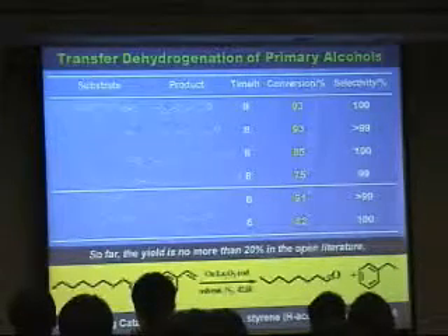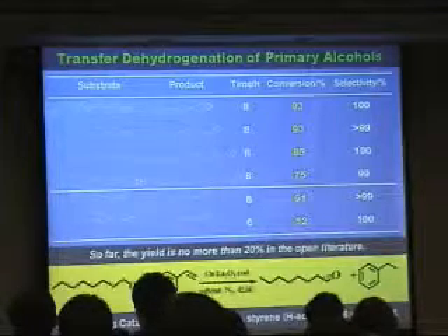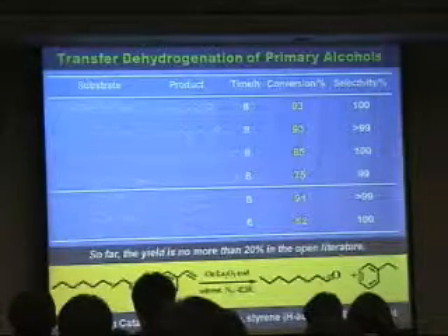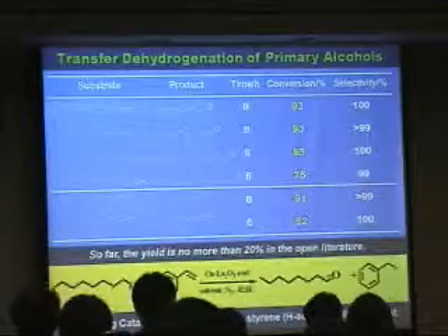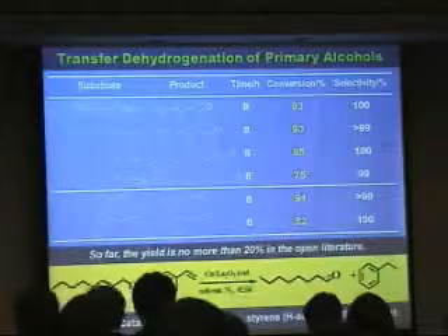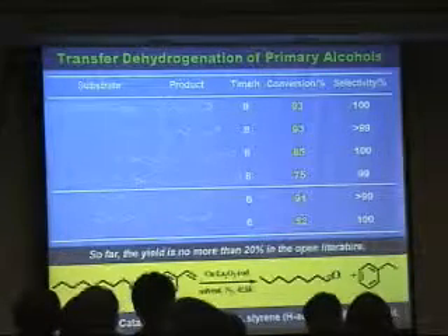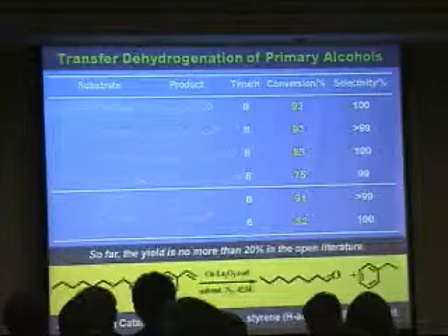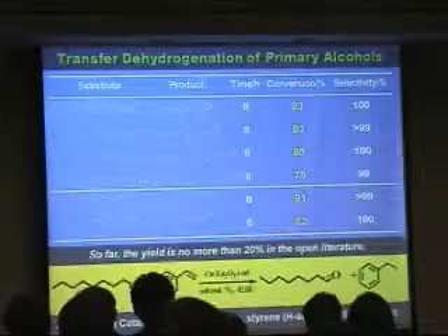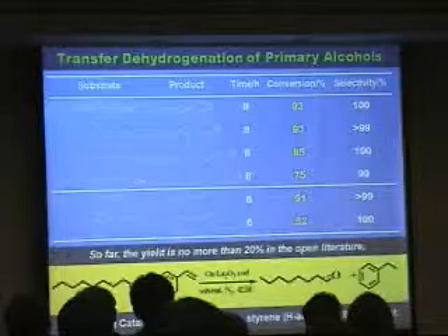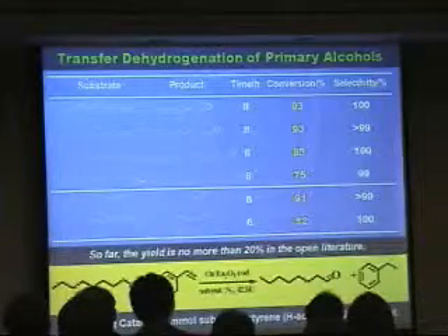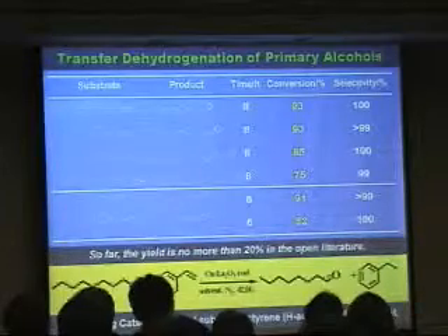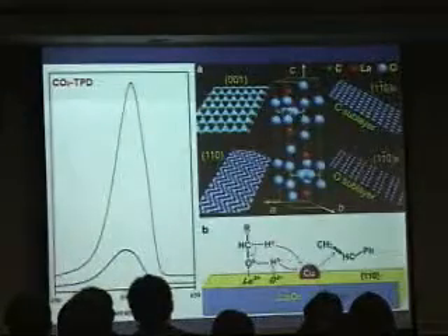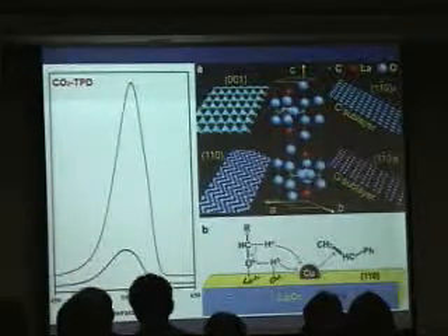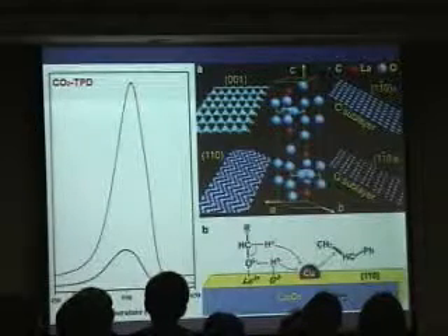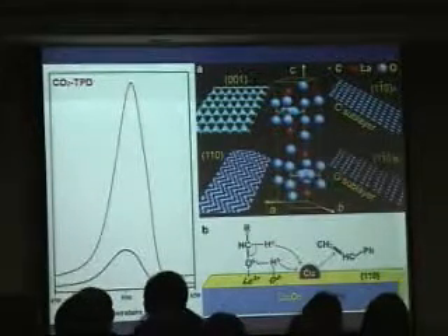And we use this process with transfer dehydrogenation. The hydrogen is removed by this olefin, and we get this aldehyde. Even for this reaction, the best yield is about 20 in the open literature. And we use this rod-shaped lanthanum oxide to support the very good small copper particles. You can find the yield is quite promising for this process. And of course, it should be much better for other alcohols that are more easily converted. So the reason is that we changed the shape of the lanthanum oxide support, largely contributed by this 110 surface.